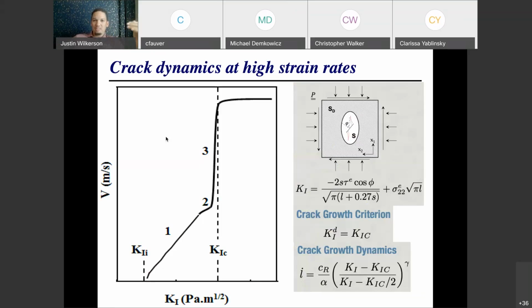The first thing that I want to mention, let's first talk about the kinetics or the dynamics of cracks as they propagate through the material. So you saw that visualization in the last video. This, on the left, is a typical kinetics diagram or dynamics diagram for the velocity at which cracks can move. So on the x-axis, you have the so-called stress intensity factor, which is a measure of the stress state right at the tip of a crack. And on the y-axis, you have the velocity at which the crack will move under that applied stress intensity factor.